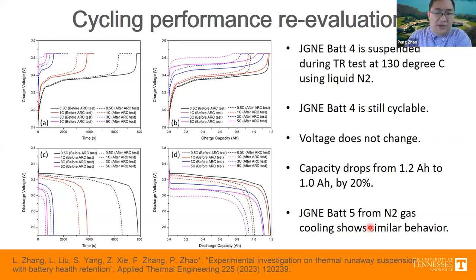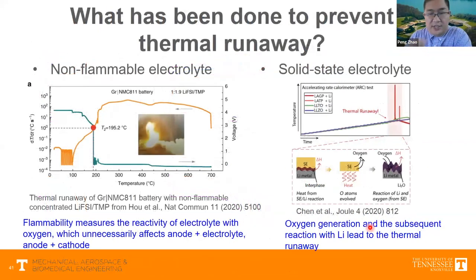So this is for LFP cells, which is a rather safe cell compared with NMC and LCO. For NMC and LCO, because the thermal runaway reactivity is so strong, the thermal stability of the separator is not a limiting step. Now, we cannot improve the safety by coming up with a better separator. There are also some trials that people have tried to prevent thermal runaway. For example, people have tried using non-flammable electrolyte, but unfortunately, even with non-flammable electrolyte, thermal runaway still happens. That's because the flammability limit measures the chemical reaction between the electrolyte and oxygen. It doesn't prevent all the other side reactions, for example, lithium and electrolyte.